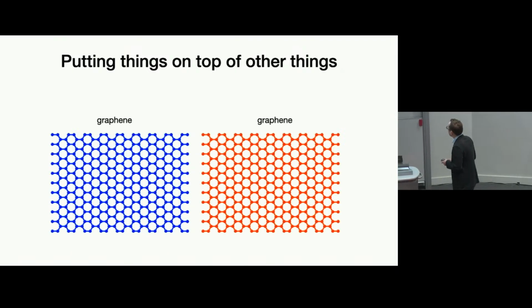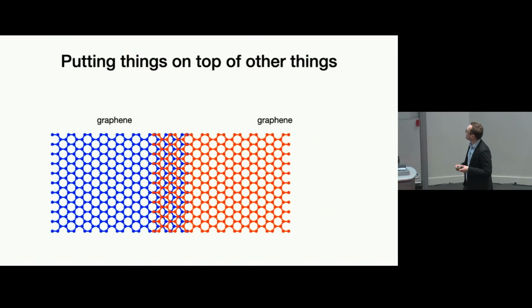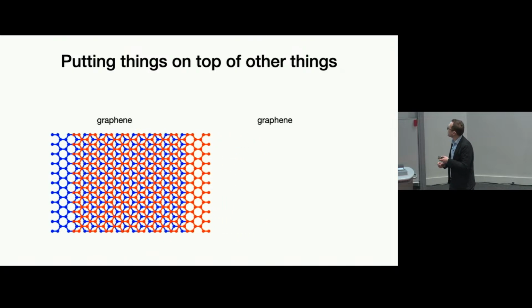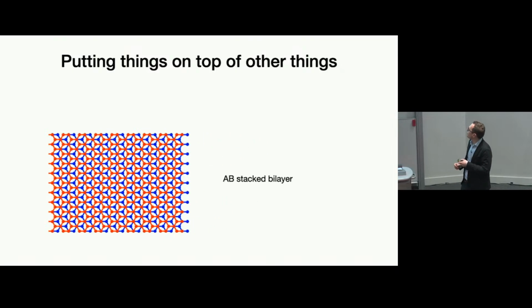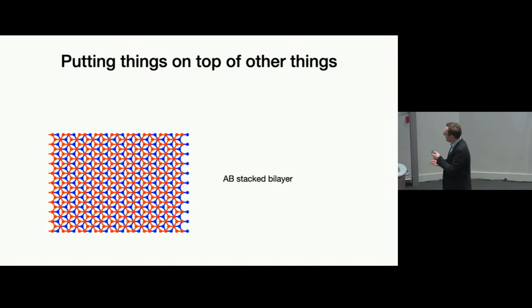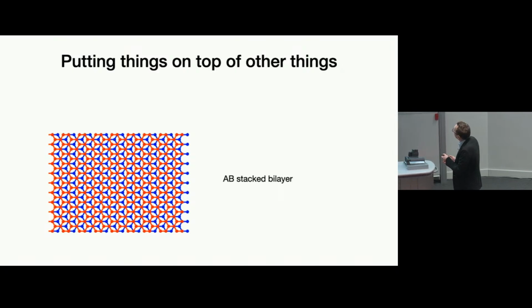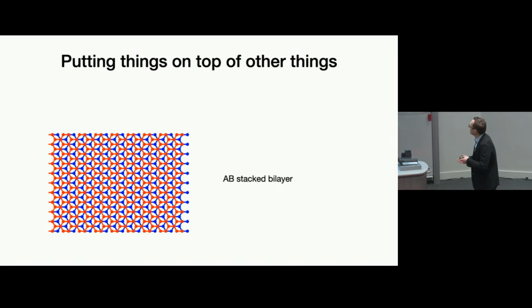But there's another way to put the two graphene sheets on top of one another, which is this one. This is the so-called AB stack bilayer, which has a much lower energy. And in this bilayer, you can see that the carbon atoms of the top layer sit in the middle of the hexagons created by the carbon atoms in the lower layer, and the other way around. So this is a very low energy stacking.